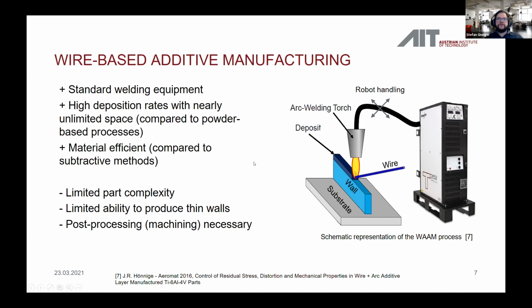For wire arc additive manufacturing, standard welding equipment can be used, and you can achieve very high deposition rates with nearly unlimited space. The space is only limited by the range of the handling device. The process is very material efficient, especially when compared to subtractive methods like milling, because you use almost the whole material coming from the wire. Again, you have some disadvantages. For example, as already said, the part complexity is limited. It depends on the wire diameter, but overall the complexity is limited. You also have a limited ability to produce thin walls. And for achieving the best results, the lightest weight, post-processing machining of the parts is necessary.